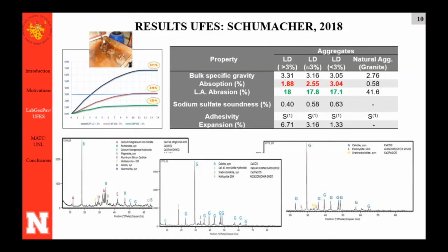And I highlighted here mainly these absorption results, and you can see the slag as is has a lower level of absorption. All the 3 slags in the 3 levels had absorption values much higher than the natural aggregate. So what do you expect if you use an aggregate that has more absorption than a natural aggregate in terms of mix design? You expect a higher consumption of binder. So we just stay with this information and let's see, this may affect our volumetrics.